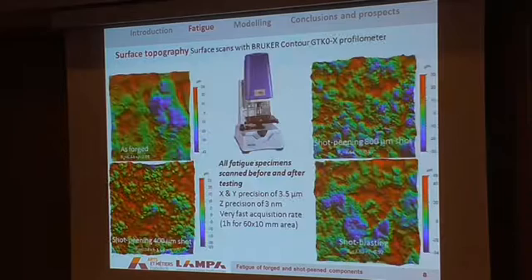So we carried out many tests, and before every fatigue test, we perform a scan of the surface of all the specimens by using a profilometer, using an interferometry method. And you can see here the example of what we can observe for the as-forged case, for two types of shot peenings with different shots, and for the shot blasting conditions. And you see here that some defects occur in some locations. And you see here the values of the average roughness, and you can trust me, you can't use this roughness to get an estimation of the fatigue strength.